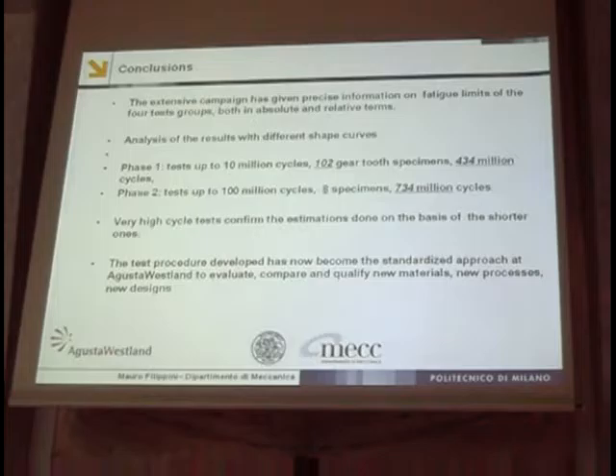We can sum up the two phases of the test. We tested up to 100 gear specimens with a duration of up to 10 megacycles for each test, 430 megacycles in total. And we have a phase 2 test on just one variant with 8 specimens up to 100 megacycles, 734 megacycles in total. This very high cycle fatigue test confirms the estimation done on the basis of shorter tests.